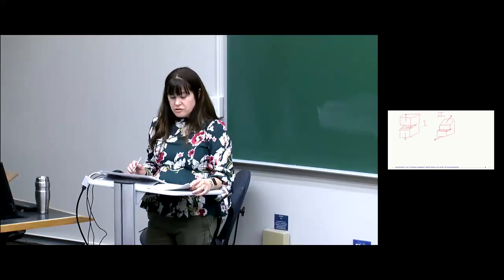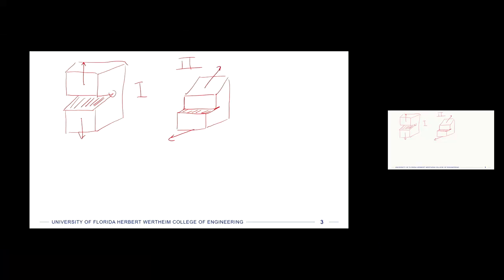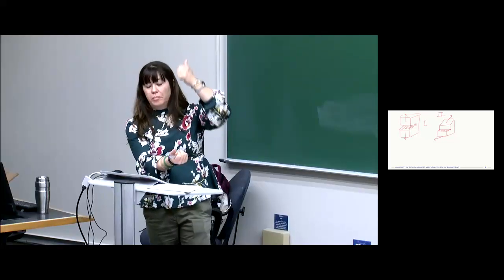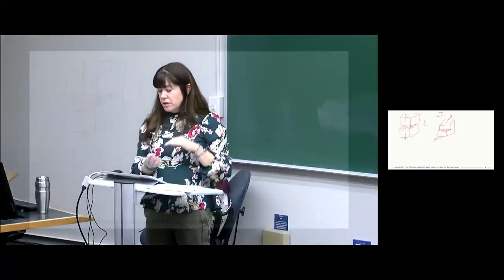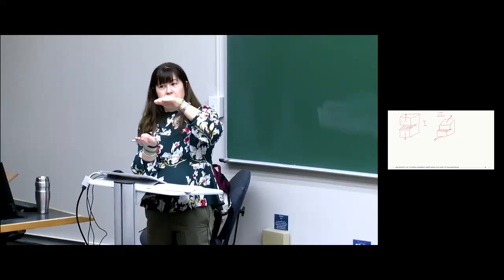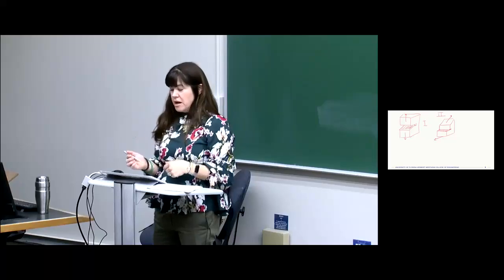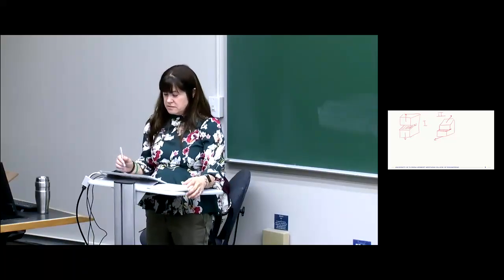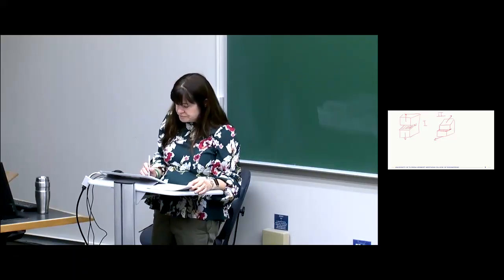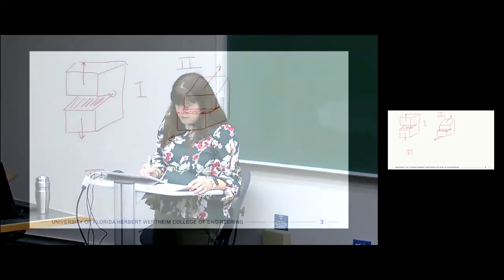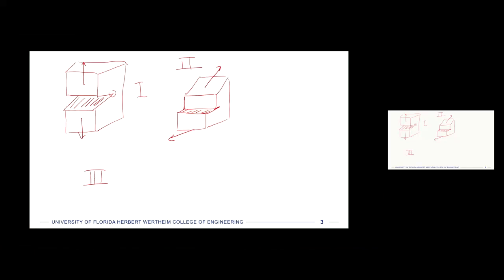And you can see now that the stresses at the crack tip are going to be very different in this case. On mode 1, you have tensile stress at the crack tip trying to open that thing up. In mode 2, you're actually compressing one side of the crack and putting tension on the other side of the crack, and it's totally in a different axis, right? So that's mode 2. Mode 3 is kind of a twisting motion. So let me do my best on this one.